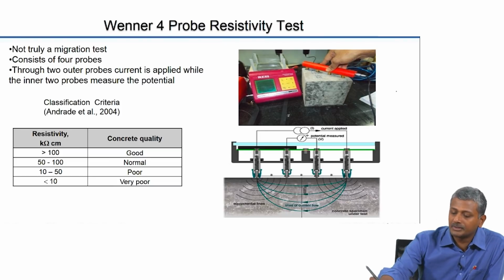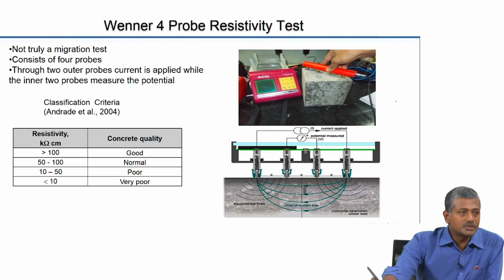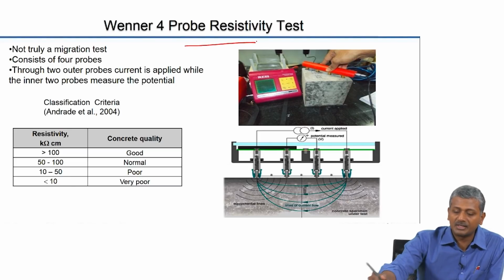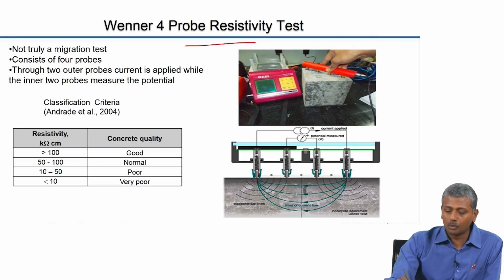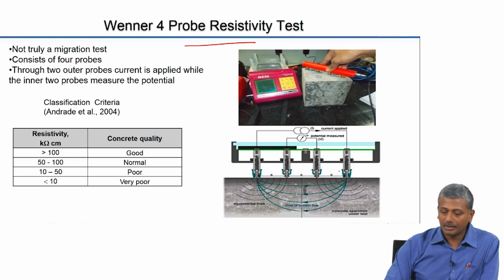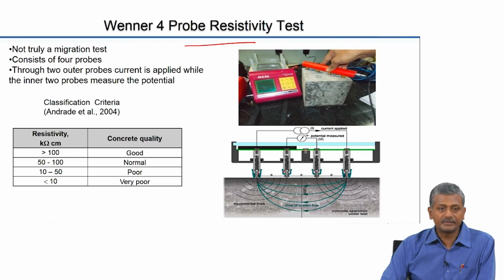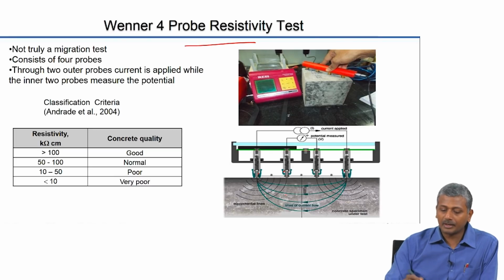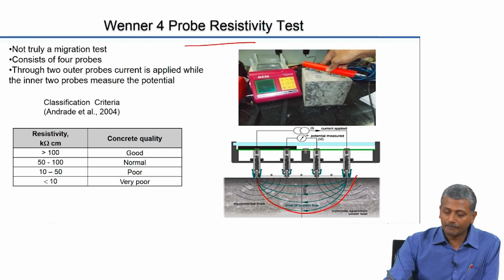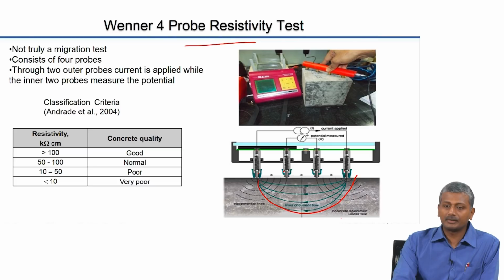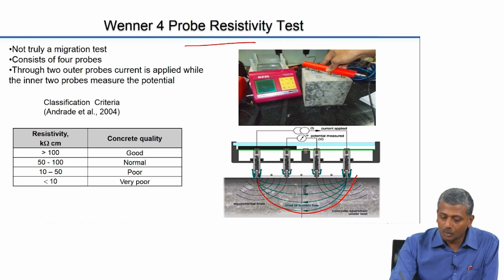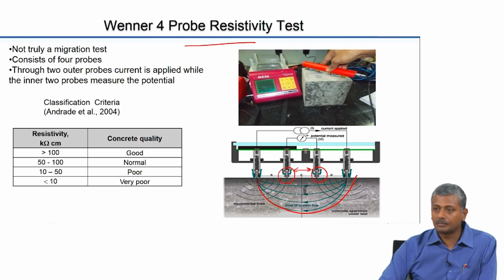One common method which is quite easy to use even on site is the Wenner 4 probe resistivity test. Here you have 4 probes that are equally spaced and placed on the concrete surface. You apply a current through the external probes, and then you determine the voltage or potential drop across the inner probes.